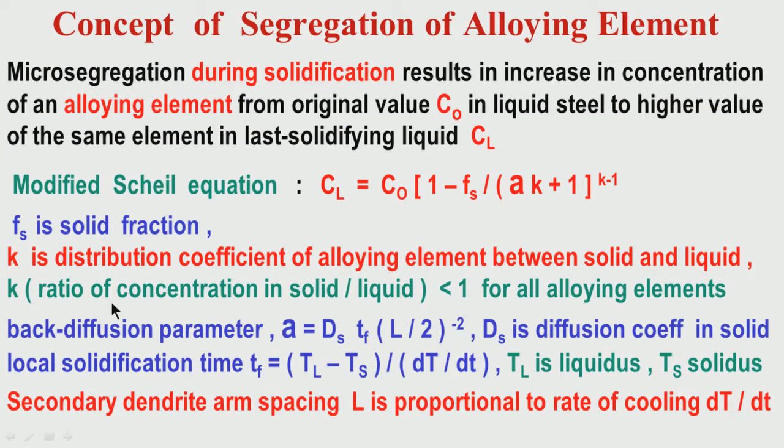So, what is happening is the final concentration in the last solidifying liquid is increasing from the original concentration by this relationship. This is dependent on the solid fraction. The higher the solid fraction, the higher is the concentration in the liquid, that is, the more is the segregation.